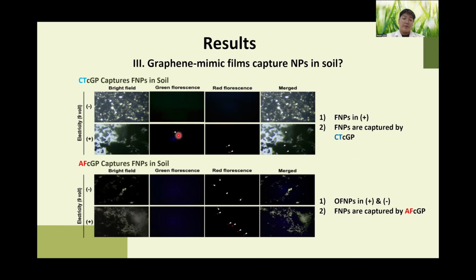As a result of observing the film's surface under the fluorescence microscope, I could detect many nanoplastic particles on the surface of both films, CTCGP and AFCGP. It indicates that both films can effectively capture nanoplastics.